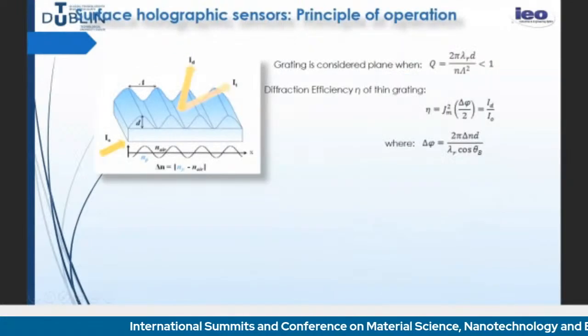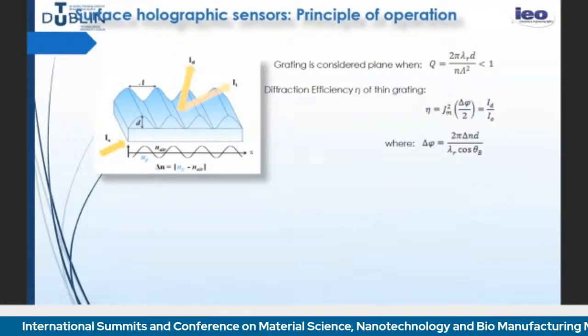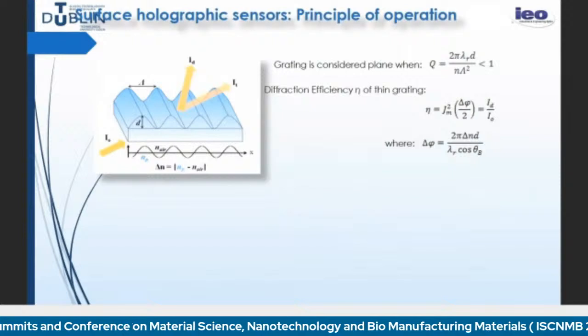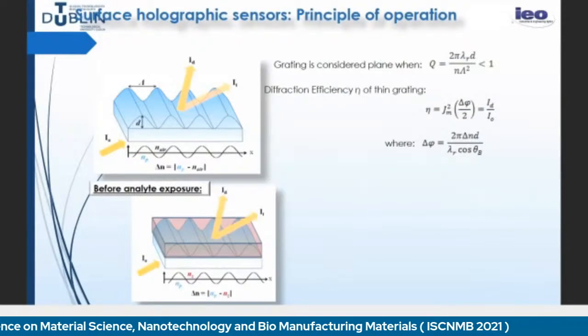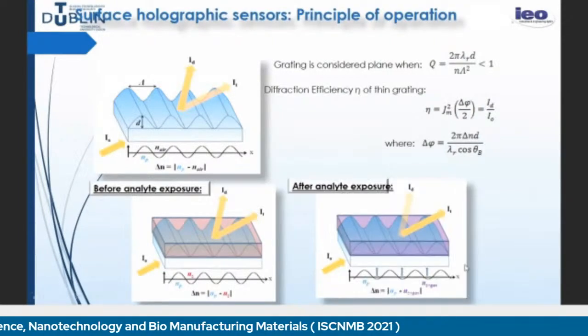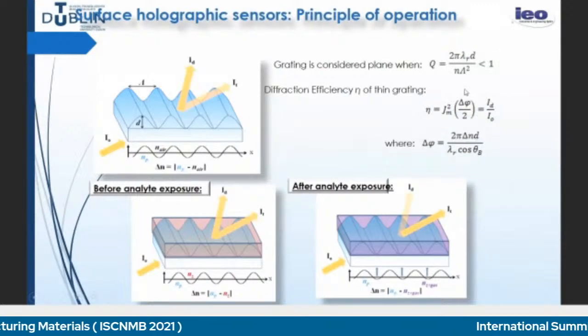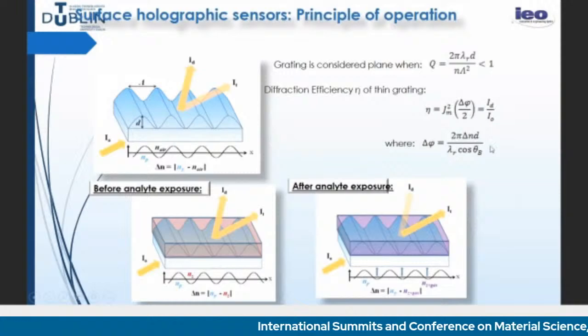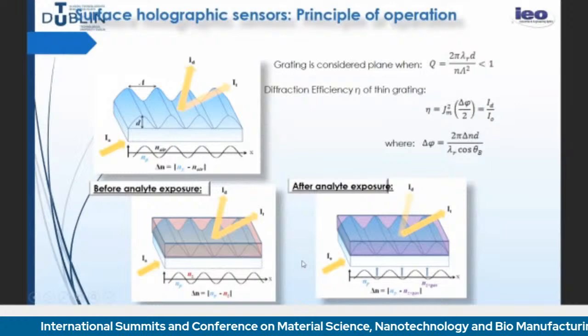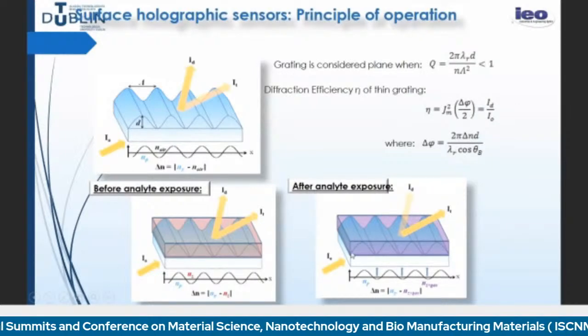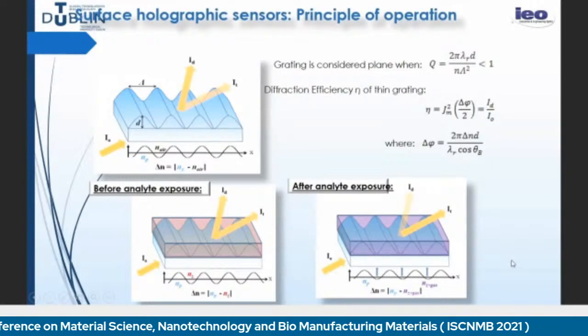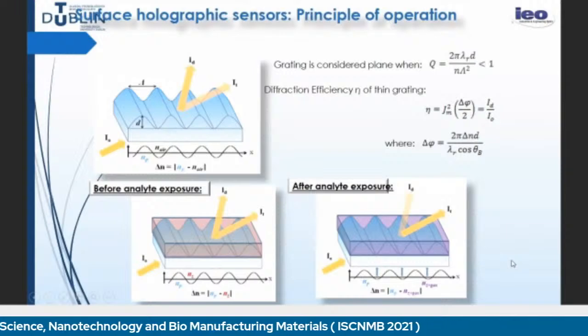So in the surface gratings, we use Raman-Nath theory to model the diffraction efficiency. This is before analyte exposure and after analyte exposure. This phase factor here is changing. The refractive index modulation is changing, because the structure remains the same in terms of refractive index. Only the top layer changes refractive index as the analyte is absorbed.